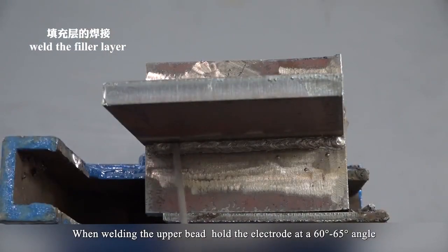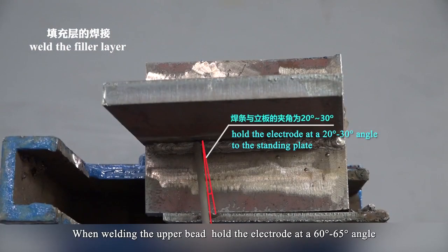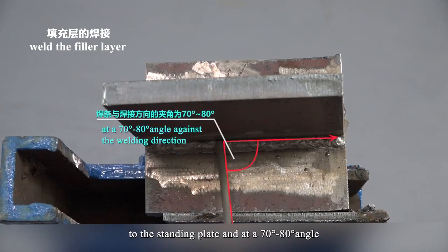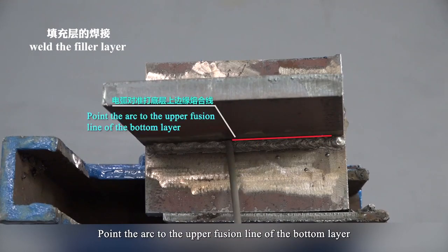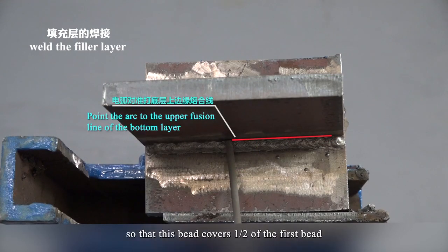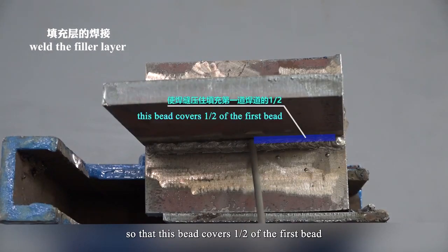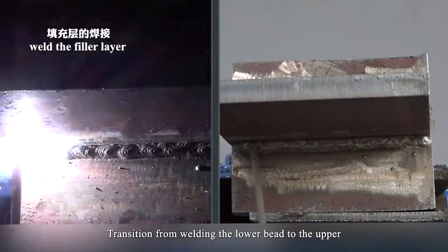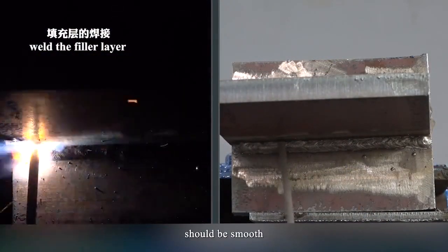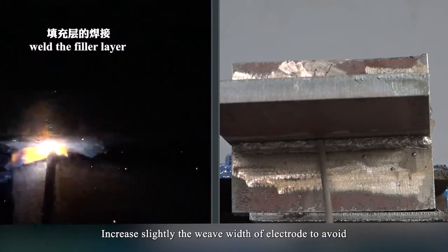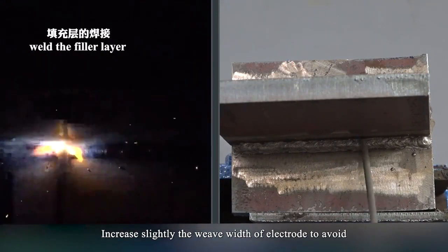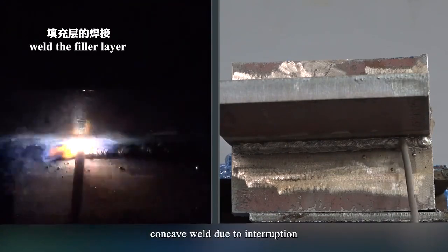When welding the upper bead, hold the electrode at a 60 to 65-degree angle to the standing plate and at a 70 to 80-degree angle against the welding direction. Point the arc to the upper fusion line of the bottom layer so that this bead covers 1/2 of the first bead. Transition from welding the lower bead to the upper should be smooth. Increase slightly the weave width of the electrode to avoid concave weld due to interruption.